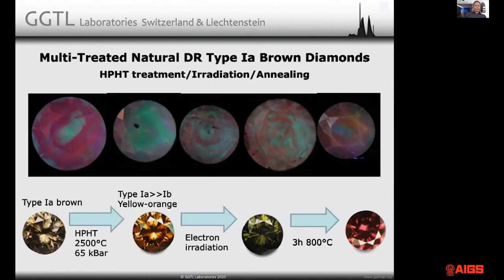If you take a brown diamond, same thing, a deformation-related brown diamond, and you HPHT it at high temperature, so you manipulate the type. You're creating a type 1A diamond with some single nitrogen. It's going to be yellow-orange in color, or somewhere in between yellow and orange. So from a regular 1A brown, you're creating a 1A diamond with some C centers. These C centers are needed to create purple color. And this purple color or red color is induced by irradiation plus annealing. Irradiation plus annealing of a single nitrogen containing diamond will always produce the NV centers, and the NV centers induce that pink to purple to red color. So this is a multi-step treatment that's being used since about, I think, 2008 or 2009 to create pink to red diamonds out of regular type 1A brown diamonds.